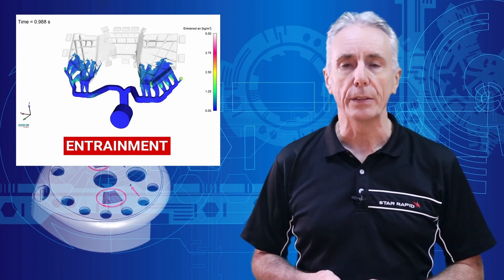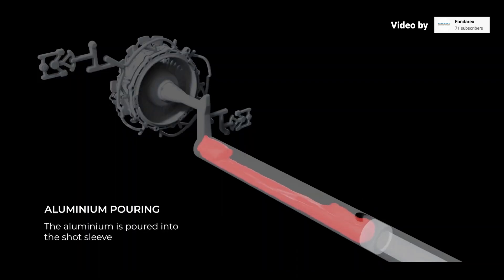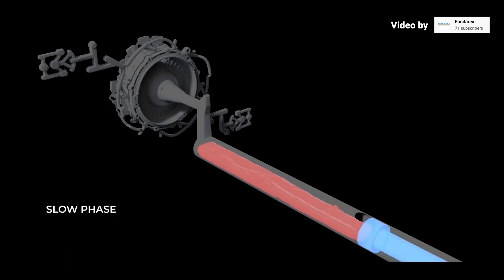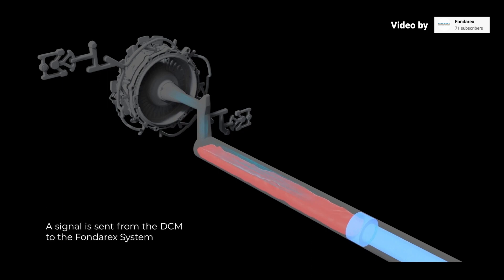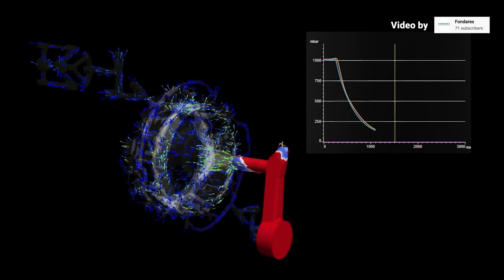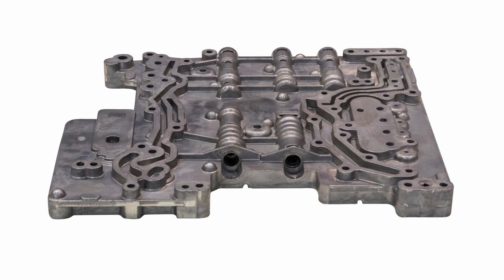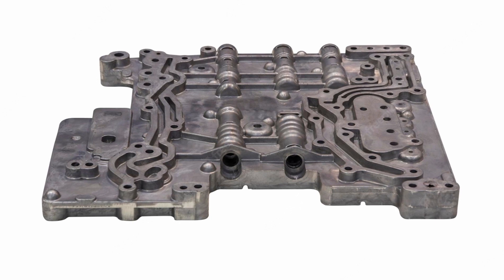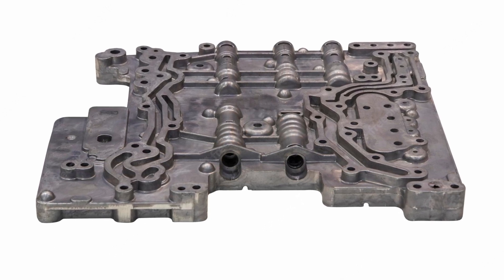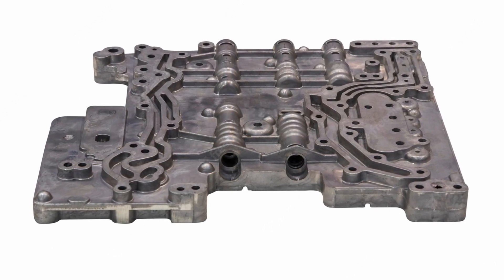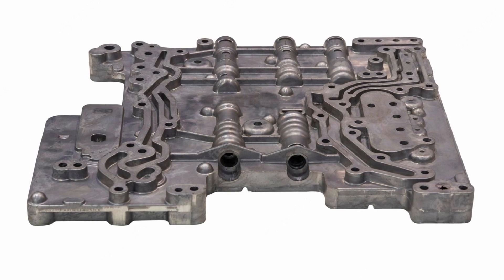Presumably because they burn to the ground. One technique that is still used is to pull a vacuum in the die, which also helps to suck the air out as the aluminium advances. Again, this is highly impractical and frankly it's better to just redesign the part and the die to avoid entrainment in the first place, or push the problem to a place on the casting where it doesn't matter. Consult your PDC supplier during the design phase.